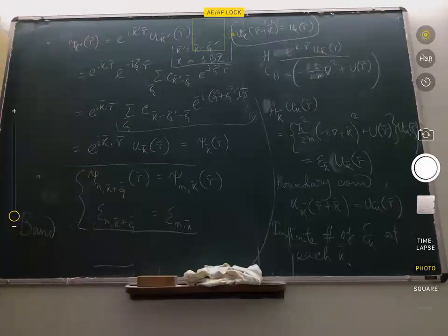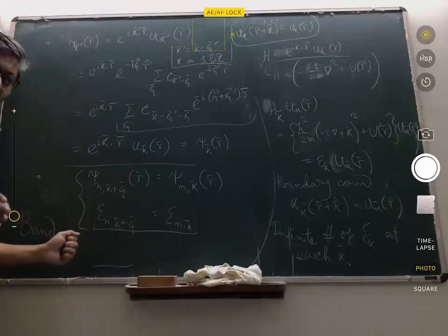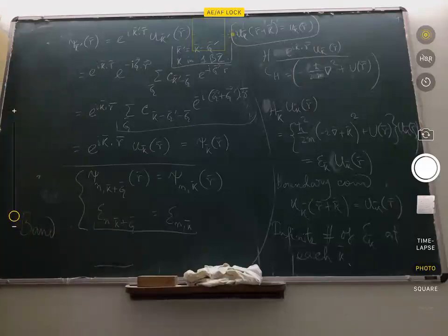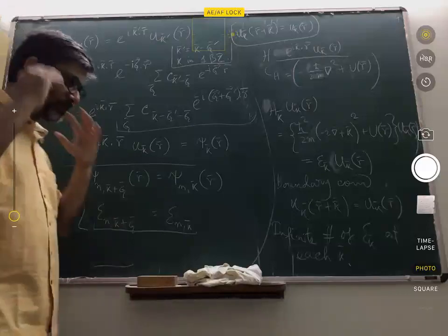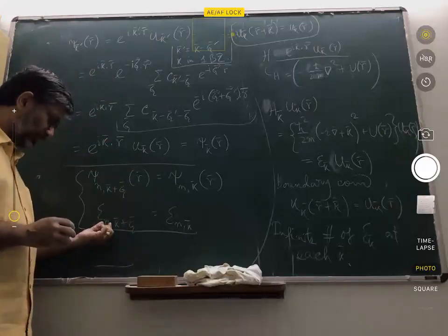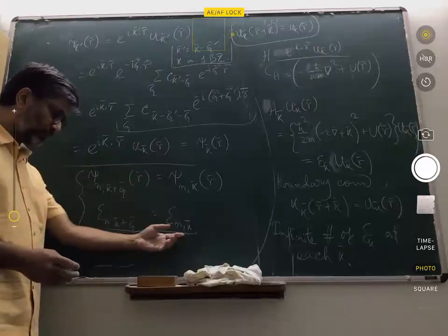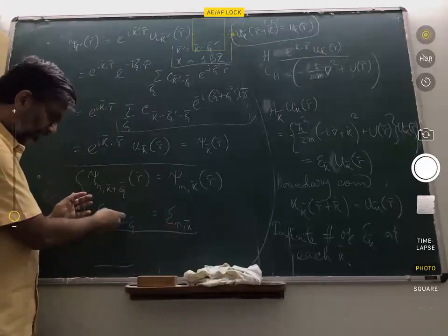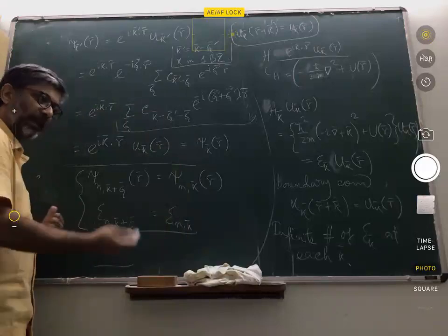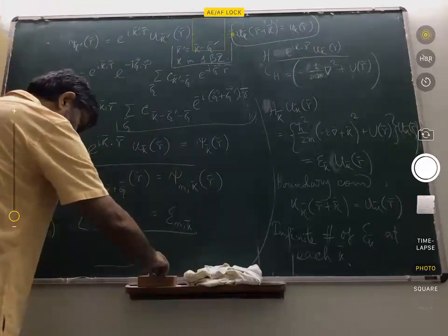Remember, these energies are functions of three coordinates: kx, ky, kz. For a three-dimensional solid, k space is three-dimensional. So having this mental picture for epsilons, these bands, is very, very important. I repeat that I designate an energy state with an n such that as I vary k, this energy changes, but when I move by a reciprocal lattice vector, the value comes back to the same. So epsilon k plus g becomes equal to epsilon k. This set of energies constitutes a band. So now let us try to see some real bands.